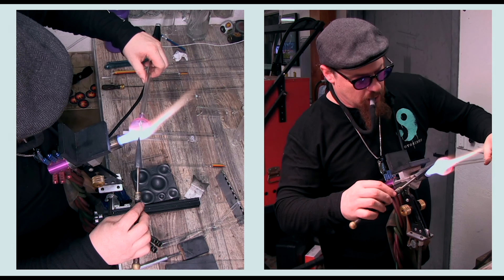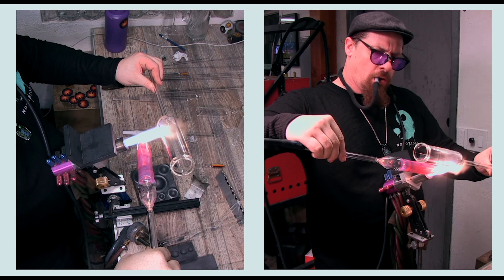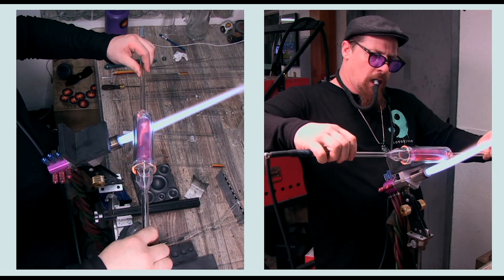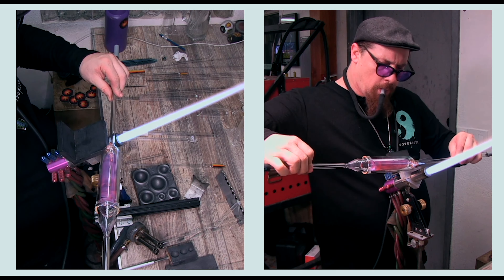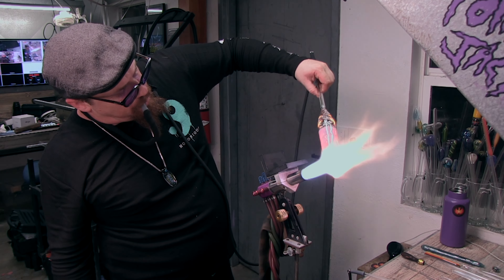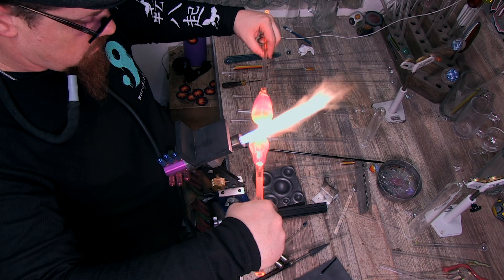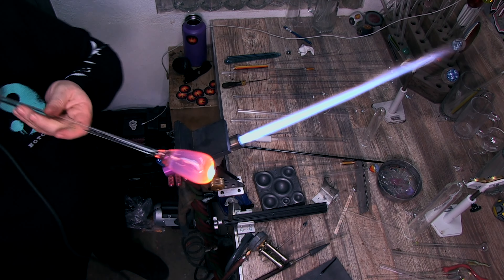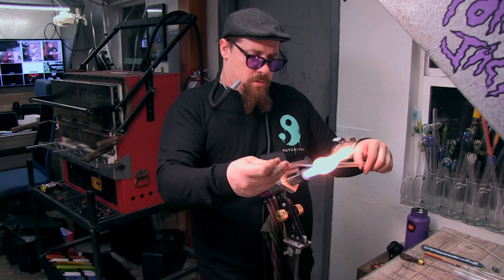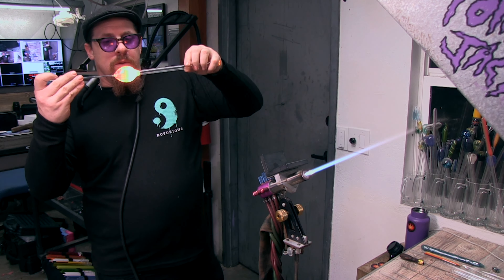The pipe shaping and styling influences other mediums — I've seen that with woodworking and painting, where it's clearly influenced by pipe culture. The pattern work and techniques we've developed through having this slightly stiffer glass has really evolved into its own medium. The other critical point about borosilicate being stiffer is the resistance to thermal shock. That resistance compared to soft glass makes it possible for us to make complex sculptural pieces by heating up only a small area at a time. You could never do that with soft glass — point heat like that. You really have to keep the whole thing hot in soft glass. You can table-cool things and go right back, or even put something complicated in the kiln and then attach a component by heating up that one area outside the kiln — that would still be dangerous in a soft glass structure.